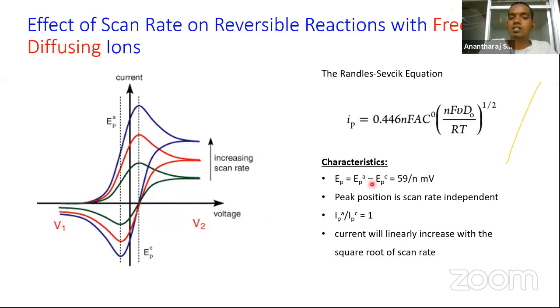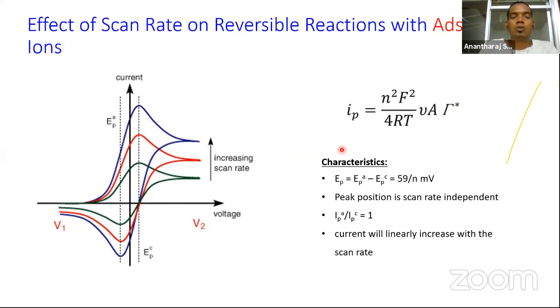This is very important, and this is defined by the very famous Randles-Sevcik equation, which helps us understand how peak current will increase with scan rate for a given analyte if it is undergoing a reversible diffusion control reaction with freely diffusing ions. In this case, we require the diffusion coefficient value and the absolute concentration in order to determine the peak current, before performing voltammetry, just from varying the scan rate theoretically. So this is what we see. So what happens if the reaction is reversible, but it is not occurring via freely diffusing ions?